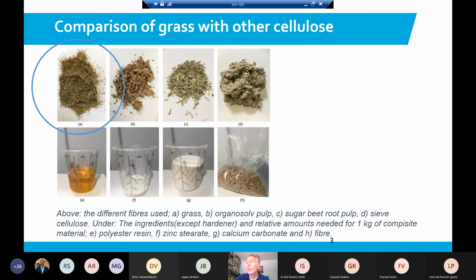When we look at waste fibers in composite materials, it's very important to see what the value of these fibers is compared to the fibers we're using at the moment. In composites, glass fibers are being used, and in biocomposites, flax fibers are being used. So the first step is to evaluate whether these grass fibers have comparable mechanical properties relative to the price. If they're much cheaper and the mechanical properties are much lower, then you can have an interesting material. So value over price is very important. Value is not only mechanical properties, it's also lifetime expectancy and, for instance, shrinkage or weight. So there are more sustainability aspects to look at if you look at the value.